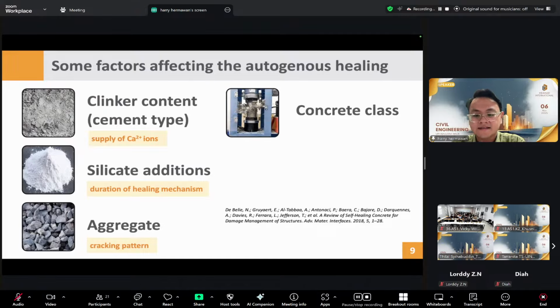Next is the concrete class. So concrete class may also contribute to the healing effect. For instance, if you are designing a high strength concrete with a low water to cement ratio, it will contain a generous amount of unhydrated cement particles that can later grow a sufficient amount of calcium silicate hydrate, calcium hydroxide, and also ettringite as a result of the ongoing hydration. So this basically determines the healing effect.